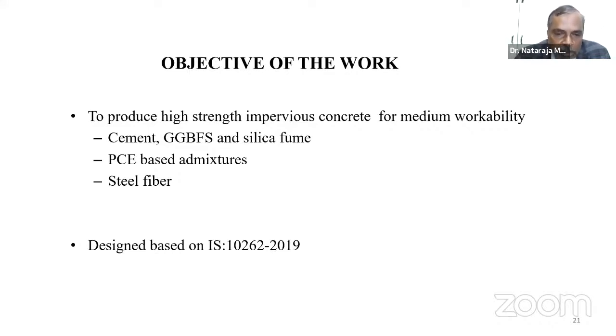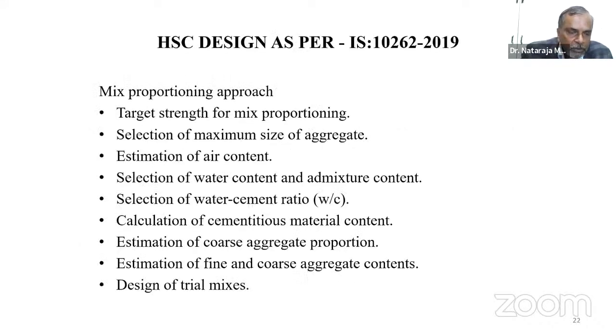of water. Means that your water cement ratio has drastically reduced from say 0.6, though not permitted, 0.55 permitted, to as low as 0.3, and of course very close to that. Thereby the concrete is definitely M60, and of course even a higher order of strength can be designed. And of course we also tried with steel fiber, as another work where some ductility part of the concrete can also be appreciated. So there are 9 steps in the mix design, which is already known to the faculty.